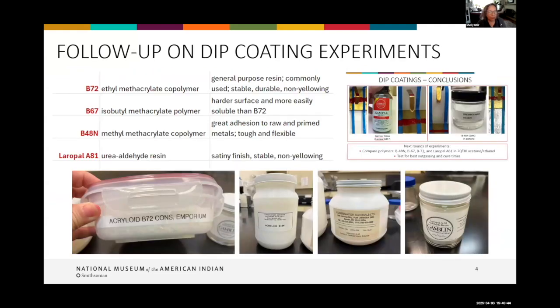So at that talk, I noted several follow-up goals that we had for continuing these collaborations, one of which was a deeper dive into four dip coating recipes. Paraloid B72, because this is already commonly used in our field. B67, because I was curious about its hardness and sheen. B48N, because it's a Paraloid that's formulated to adhere to metals, so that seemed like a good one to test. And Laropal A81, because we had liked its properties from the earlier Gamvar gloss test, and I wanted to try a non-proprietary recipe. We chose to use the 70-30 acetone ethanol solvent mix because the ethanol slows the evaporation rate for a slightly longer working time with fewer bubbles than the acetone alone.